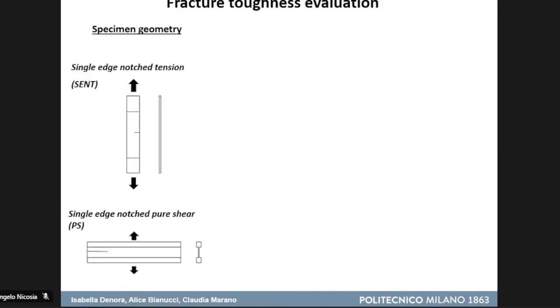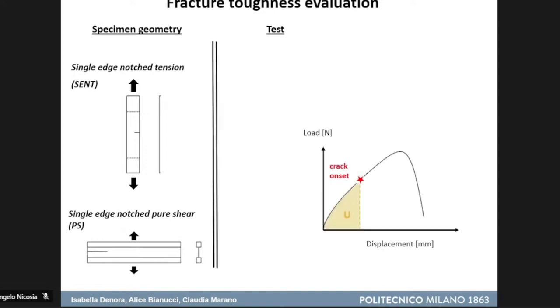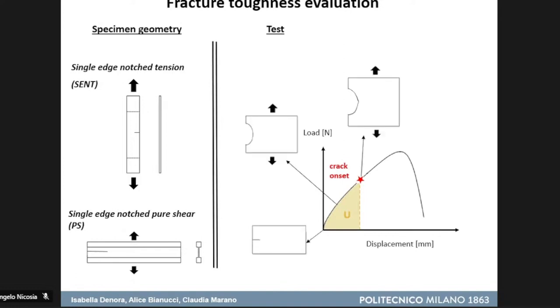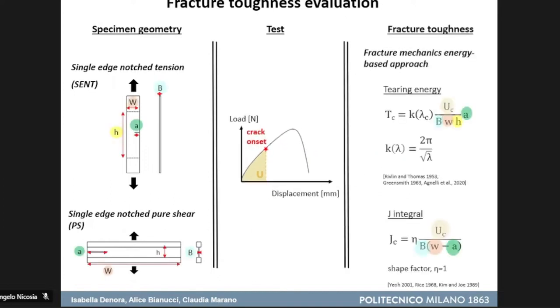And we have performed the fracture test in different geometries. For example, this that is a single edge notch in tension, and this that is a pure shear condition. Both specimens have been notched before the testing. And we performed tests with a test machine to obtain the load displacement curve. So at the beginning of the test, the notch is closed, then it opens up to a moment in which the crack starts to propagate. It's called crack onset, and we have evaluated the fracture toughness by these types of formula that are linked to the geometry of the specimens and on the input energy up to crack onset.